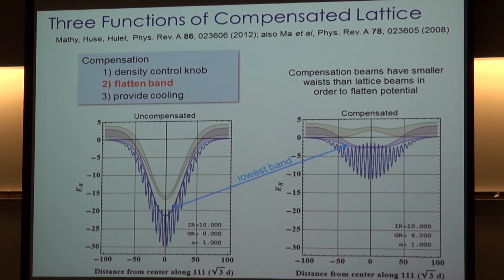And so that offers another advantage as well. There's a lot of work currently on making potentials that are very square. And this is not a square potential. In fact, for this kind of work it would be a disadvantage because then you'd have to have exactly the right number of atoms to give you exactly 1 atom per site. But it makes the potential with much less curvature, and therefore you can increase the volume over which you create the phase of interest.